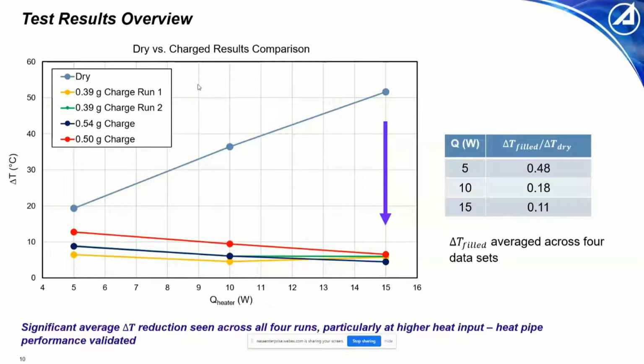So at 5 watts between those 4 curves, we averaged the y-axis value, the delta T value. We do the same for 10 and 15 watts. And then if you take that value, we call that delta T filled at a given heat input value. If you take the ratio between that and your delta T dry, which is that top curve, you get the numbers in this table here.